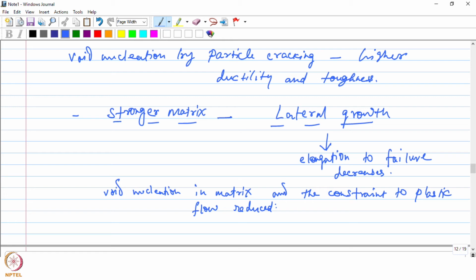Which will result in a lower ductility. So as you could see here, this is not only about the void nucleation rate, but it is also about the matrix parameters, or the matrix aspects, as to how the matrix behaves when the composite material is loaded, right? So in the beginning, we were talking about the void nucleation rate and its correlation to the ductility. But as I mentioned, it is not only about the void nucleation which can affect the ductility, but you also need to see how the matrix will behave in the presence of the particles. Okay, so the matrix parameters will actually have a lot of bearing on the ductility of the composite material.